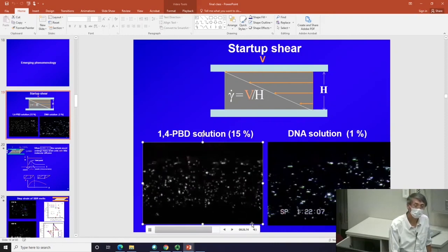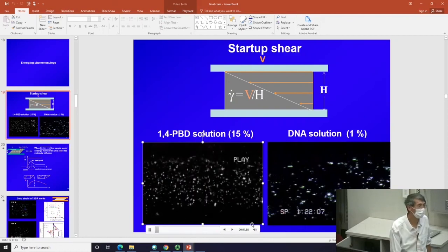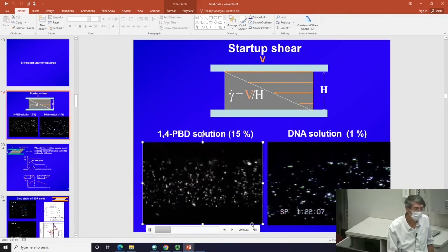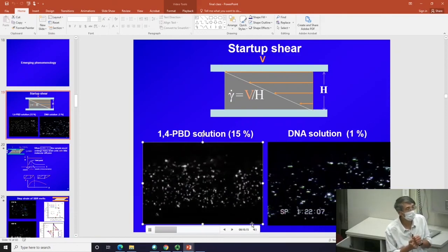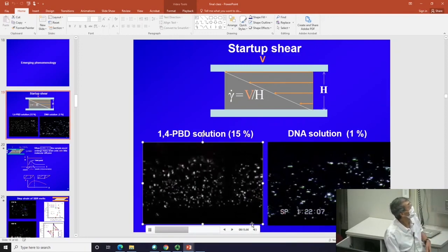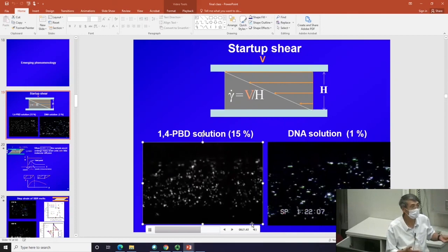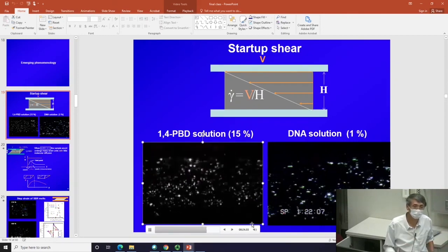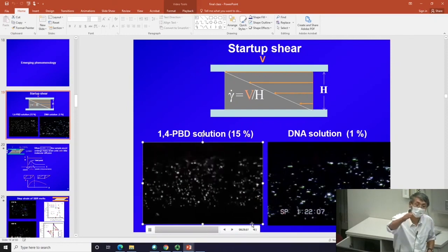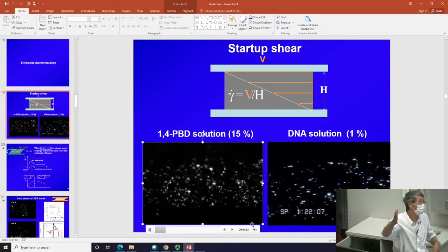It's just when you have sufficient entanglement, apparently, we're no longer stuck by this question. Apparently, you could either stay in an entangled state being sheared much more slowly or shear much more and become disentangled. And under certain conditions, these two just get stuck, meaning they are not able to switch. You can see here, the part I want to emphasize is there's no way for all the sample to shear as fast as the top part of the layer, because my V is only this small.